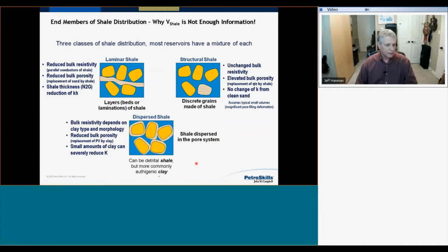In this one, the bulk resistivity depends on the clay type and morphology, because we can have this extra conductivity. We have cation exchange capacity associated with these clays, and we can have an additional source of conductivity depending on the clay type and its geometry within the pore space. We will reduce bulk porosity because we have taken 100% porosity fluid and replaced it by some volume of clay.